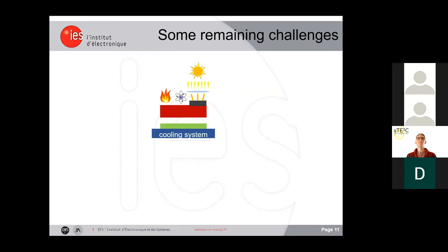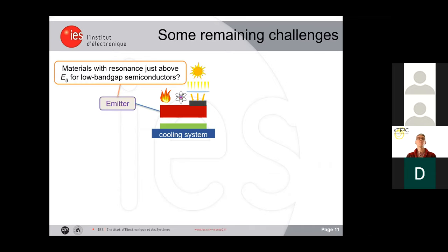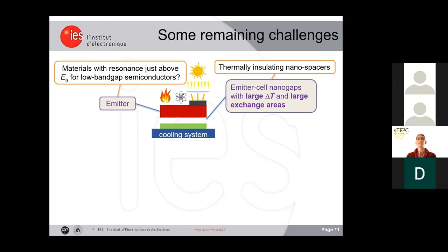Now I would like to share with you my views of the remaining challenges that we have ahead of us. For the emitter, we need to find materials with resonance just above the band gap for the low band gap semiconductors. Then thermally insulating nanospacers are likely to play a big role to build emitter cell nanogaps with large delta T and large exchange areas. In the results that I have presented before, the exchange areas were pretty small.